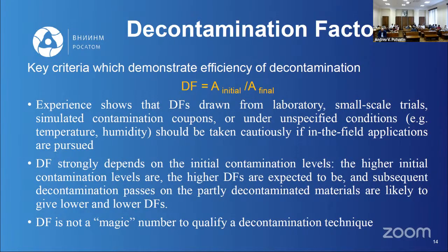And very high decontamination factors can occur if we apply decontamination for very highly contaminated materials, because it's very easy to remove high contaminations, but it's very difficult to remove very small contaminations. It's a very interesting thing, and we need to know it when we discuss decontamination factors. So the decontamination factor is not a magic number for qualifying decontamination techniques, but it's a relatively usable method for comparison of decontamination techniques.